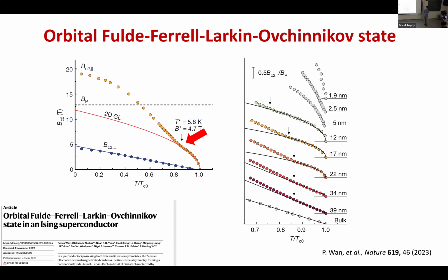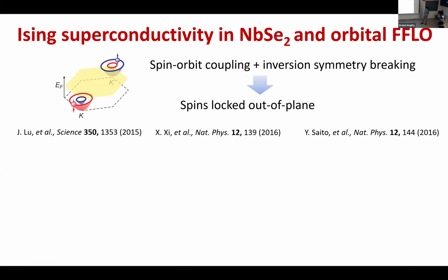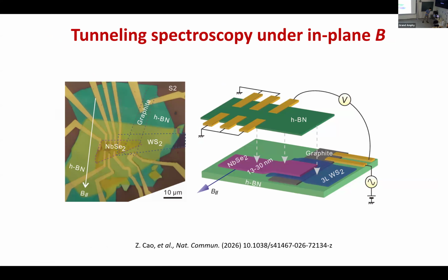So they say that globally it's inversion symmetric, but each of the layers is broken. So I'm just going back to the Xi and Mak papers. I thought that as they increase the number of niobium diselenide layers, their upper critical field fell well below the Pauli limit, so they said Ising had disappeared. So you're saying that's not true? Actually, even in the bulk, it can exceed the Pauli limit a little. And here you see that it exceeds the Pauli limit by just this much. So from that point of view, let's say it still has some Ising. I think this is so far all I want to say about Ising.